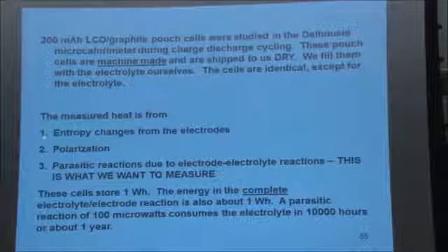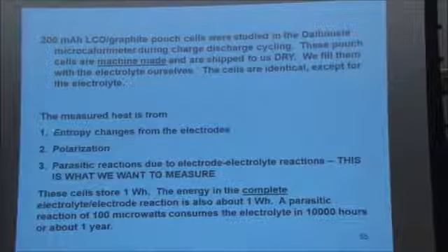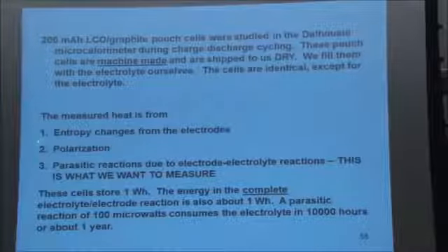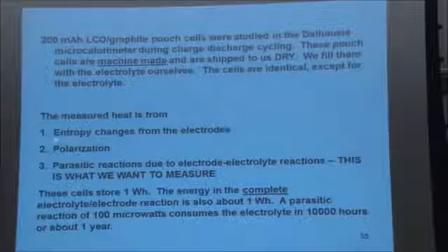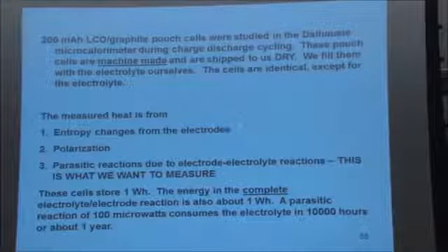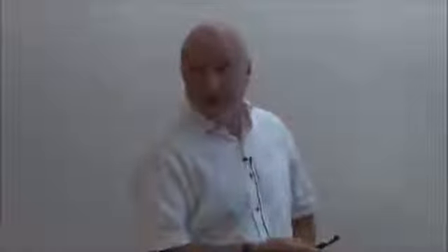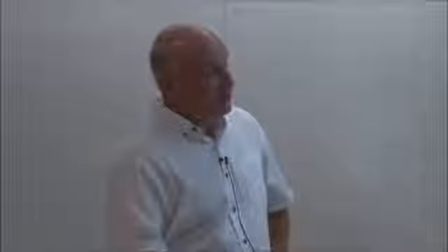So the heat that's given off in an experiment like this, there are three sources. When the lithium content in the electrodes changes, the entropy of the electrode materials changes, and there's a heat flow associated with those entropy changes. We're not interested in that. And every battery has internal resistance or polarization between charge and discharge, and there's a heat flow from that. We're not interested in that either. The parasitic reactions due to the electrolyte reactions, that's what we want to measure.